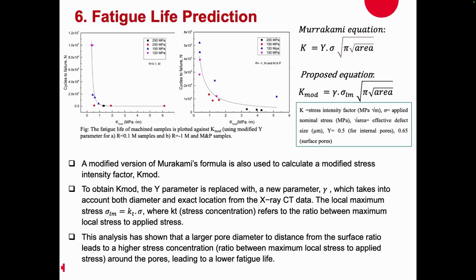Finally, we come up with a modified version of the Murakami equation by changing the factor Y to what we call gamma. This is quite important. We proposed it because we can find a modified stress intensity factor which can better capture our fatigue strength or S-N distribution, S-N graph.